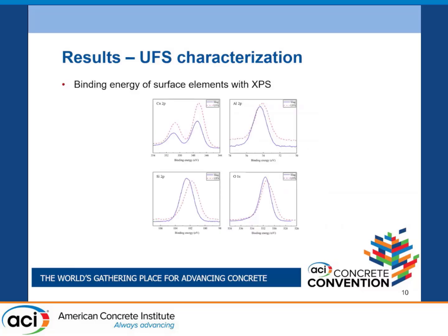The other characterization was the XPS, X-ray photoelectron spectroscopy, of the binding energy of four main elements: calcium, aluminium, Si, and oxygen. And we saw a decrease in the binding energy of these elements after ultrafine grinding, which means that they can be involved in the reactions more easily, so the rate of reactions will increase.